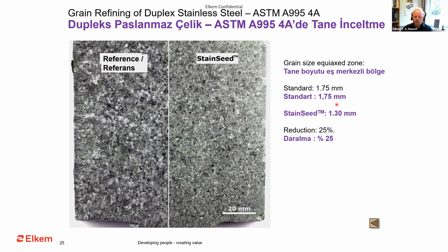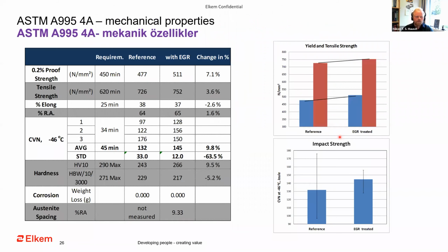So the actual grain size in the equiaxed zone was 1.75 millimeters. And when they started to use StainSeed, the grain size in the equiaxed zone was 1.3 millimeters. So there was a reduction of 25%. So we're still at the 4A duplex grade mechanical properties.